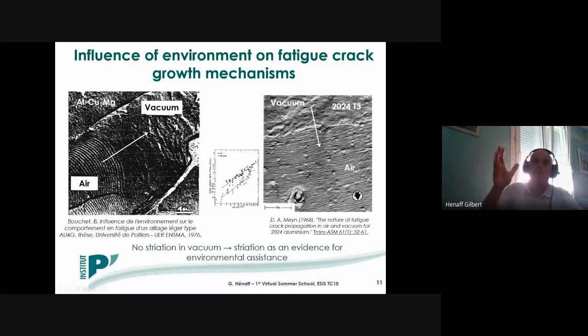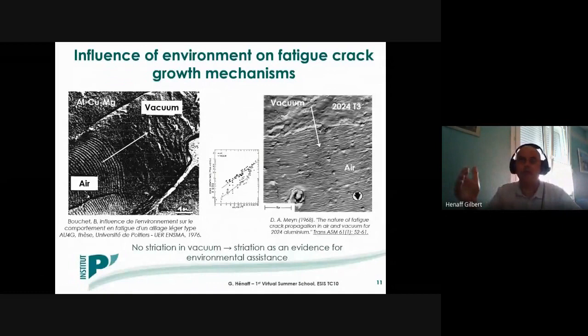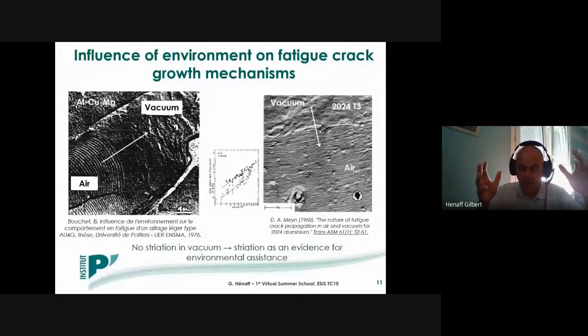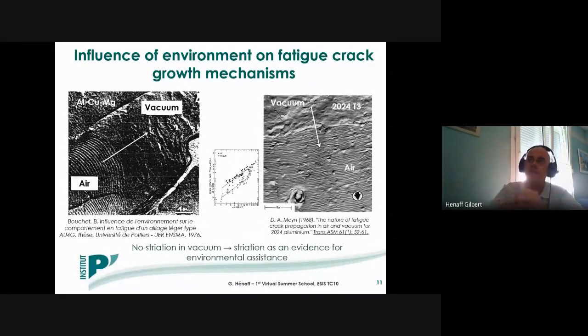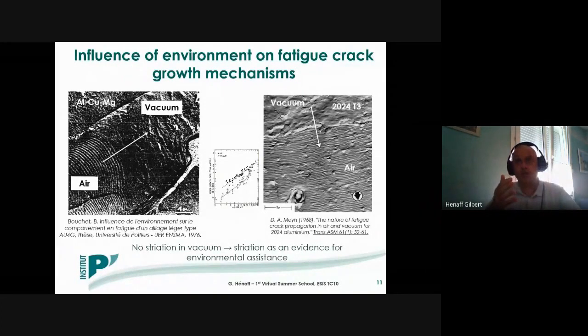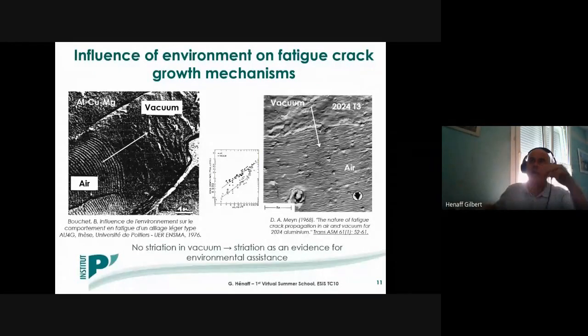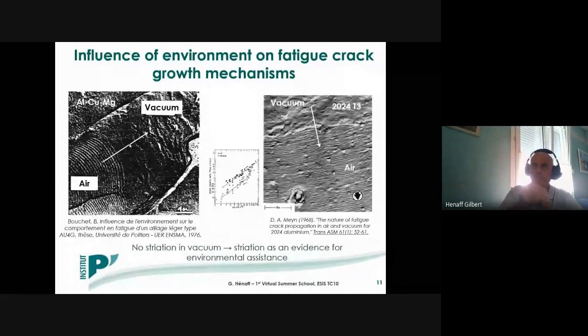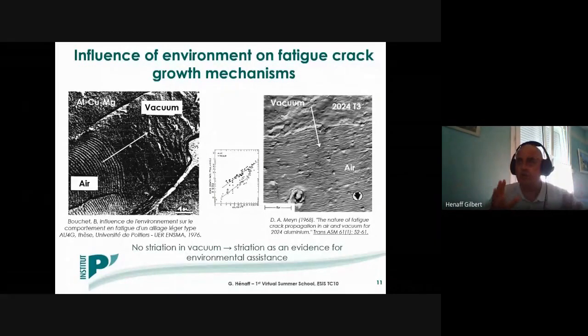And as you might know, what you can read in textbooks is that generally fatigue crack propagation, especially in these alloys, is associated with the formation of striations on the fracture surfaces. And indeed, in air, you observe in that case quite nice striations. However, when you switch to inert environment with the same load amplitude, of course, you can see that you have a disappearance of these striations, okay?